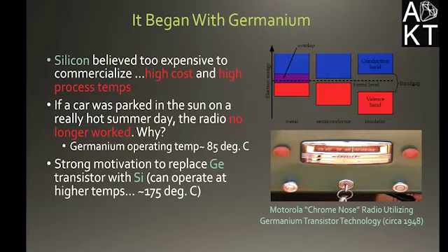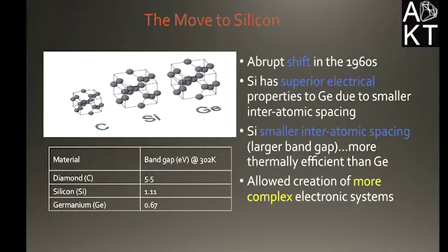So there was a strong motivation to switch away from germanium and over to silicon, which could operate at much higher temperatures, 175 degrees C. So the move to silicon happened very, very abruptly in the 1960s. Over the course of just a few years, silicon was virtually everywhere in this technology.